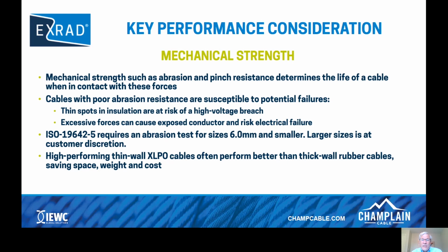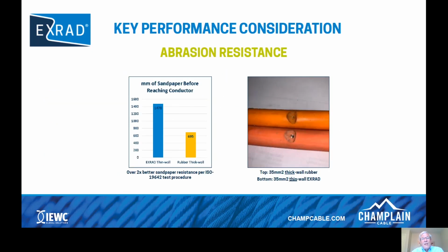High-performing thin-wall XLPO cables often perform better than thick-wall rubber, saving space, weight, and cost. The next two slides are pretty interesting. We did an abrasion test on a rubber thick wall cable and on an XLPO X-Rad thin wall cable. Most people would think that the thick wall would give you added insurance for safety, but actually the contrary is true. In this sandpaper abrasion test, you measure the length of sandpaper before you reach the conductor. The length of sandpaper on the rubber thick wall was 695 millimeters. On the thin wall, it was 1,478, more than double the abrasion resistance of the thick wall cable.